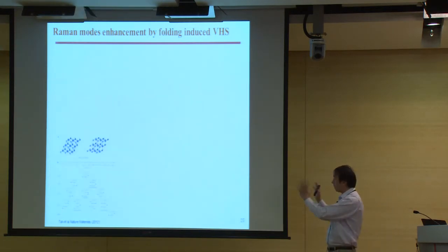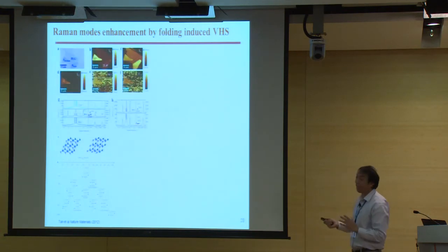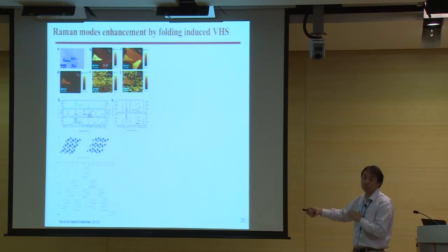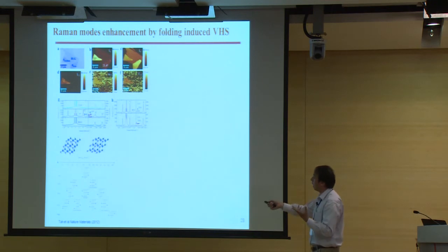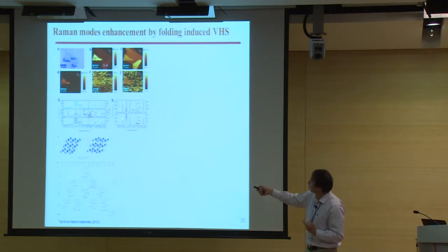For this part, my main interest is still the shear mode. So what happens to the shear mode in this so-called G resonance folded Raman? Of course, to have a shear mode, we need a bilayer or thicker, so this is basically a 2 plus 2. You see here the spectrum, I'm sorry it's a little bit small, but this is a low-frequency Raman spectrum. The shear mode is located near 30 wave numbers.